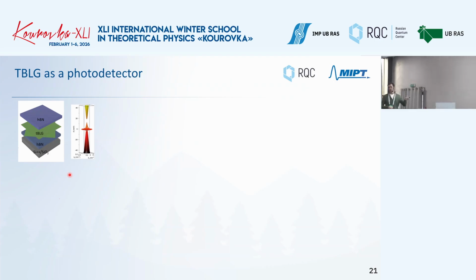It is used for photodetection for some reasons. First of all, it can indeed absorb light. A single monolayer of graphene absorbs 2.3%, which is quite large for a monolayer material. And it absorbs in a broad spectral range, almost the same everywhere. But people use graphene for photodetection not because it absorbs everywhere, but because the temperature to which the electrons heat up is very large, so it can be a very sensitive detector.